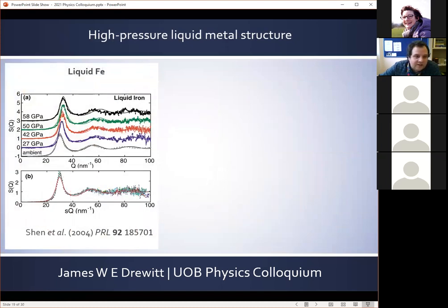So I'm going to consider some high pressure liquid metal structure, where at ambient pressures liquid metals can be approximated more or less as simple liquids. And by this I mean their atoms arrange in an optimal packing similar to ideal hard sphere structures. So I show here an example for liquid iron, measured in a laser heated diamond anvil cell to pressures up to around 60 gigapascals by Shen et al. And they observed very little change in the structure of liquid iron with increasing pressure. And in fact, at 60 GPa, liquid iron remains consistent with a close packed hard sphere liquid.